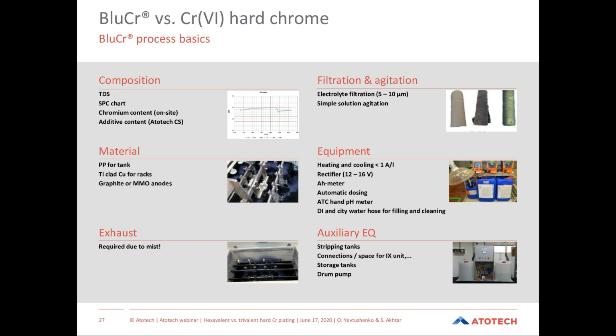For both processes, you will need to use exhaust due to misting, due to hydrogen evolution, which takes some parts of the electrolyte, and you will have misting. For blue chrome, you will need some basic electrolyte agitation and some filtration is required. Also, for equipment, apart from other things which Shakil already mentioned, it is important to have a pH meter because pH is important for blue chrome. And you may also need some auxiliary equipment, in fact for both hexavalent and trivalent, but for trivalent, for example, you might need an ion exchanger to remove some contaminations.